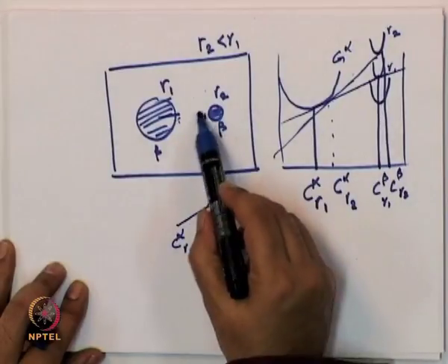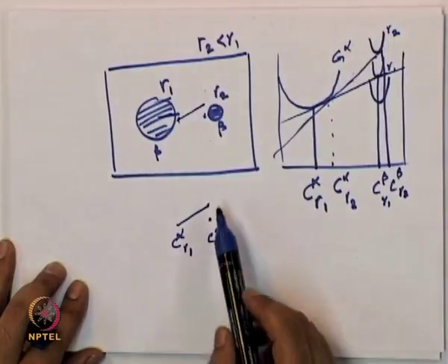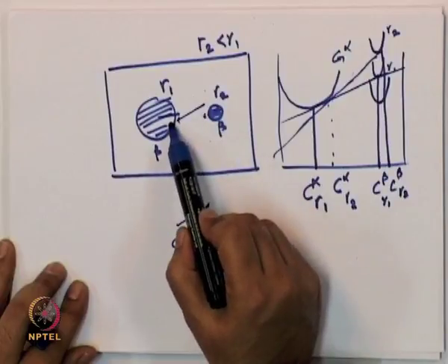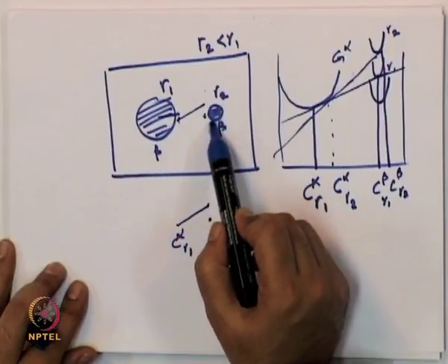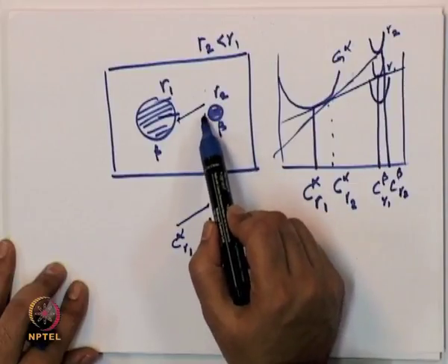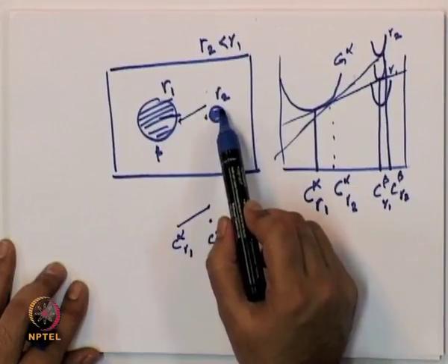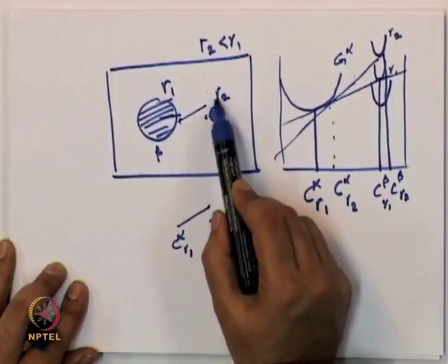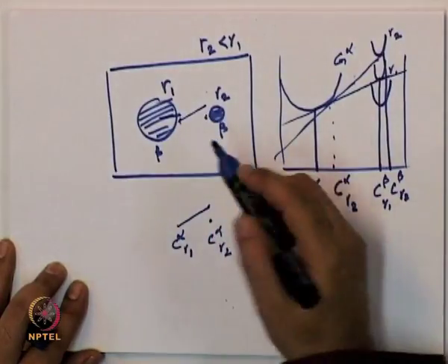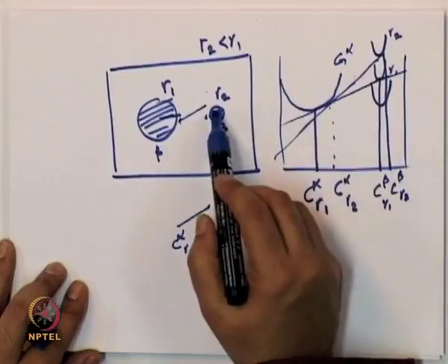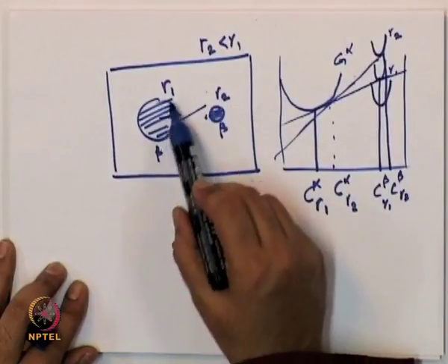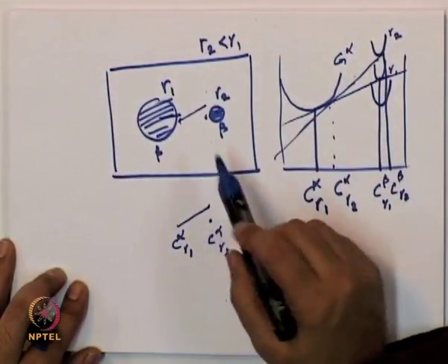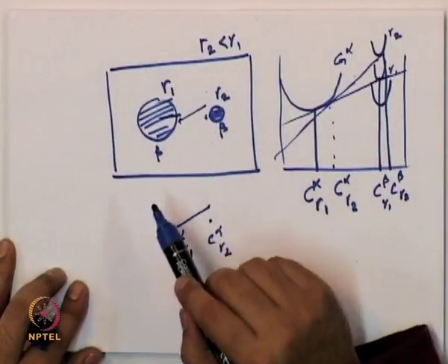So, there is a concentration gradient, the concentration in alpha is like this, which means more atoms from here are going to move towards this, which means this is then going to shrink because it has to maintain this composition outside, and as it shrinks the equilibrium alpha is still going to be higher. So, as it shrinks this is going to be self reinforcing. So, this precipitate will become smaller and smaller and eventually disappear, and the diffusion will make this grow. So, this is the diffusion limited coarsening, and as you can see the driving force for coarsening comes from what is known as the Gibbs-Thomson effect.